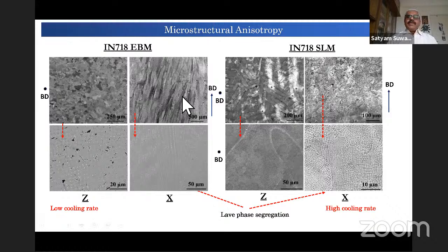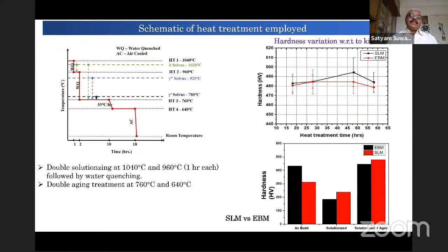EBM is a very important process because in EBM we can keep the substrate at a higher temperature generally, and this leads to very precise control of the microstructural features by controlling the cooling rate. We can do it. These superalloys are also associated with lots of precipitate phases, which are really their inherent attributes. Each of these processes has a different range of phase stability and precipitate stability that needs to be taken care of.